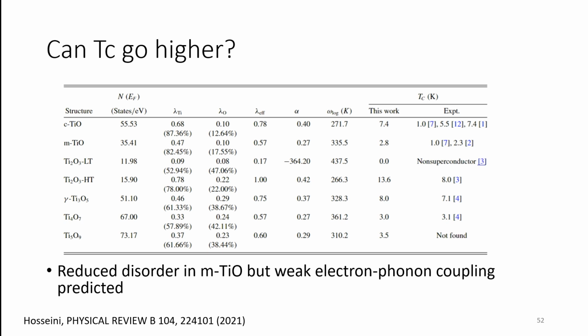It turns out that we found a theory paper which did calculations, so you can calculate the electron-phonon couplings in these materials. And what they found again here was that for this monoclinic phase that we find experimentally, the electron-phonon coupling is relatively weak, and the TC that they predict is actually very close to what we think we're observing experimentally. But they also find some other phases here where if we can reduce this order, we can potentially increase TCs, for example, in this phase, up to temperatures above 10 Kelvin.